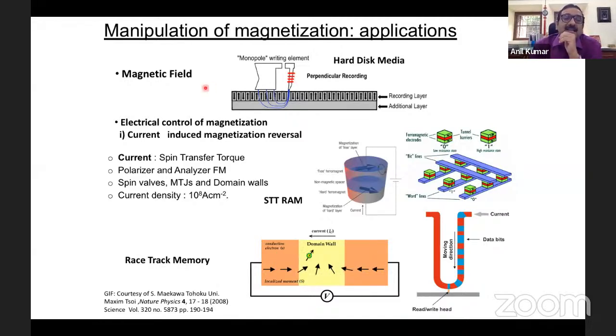So people found that there is a mechanism called spin transfer torque, where you create a beam of spin polarized electrons and it passes through this material. And in this part of the material, the magnetization is in this direction. This part of the material, magnetization is in this direction. Now, if I pass a current of spin polarized electrons, what is a spin polarized electron? You have a mix of up spin and down spin electrons. Now, predominantly one type of electrons I choose, and pass through this material. What can happen?